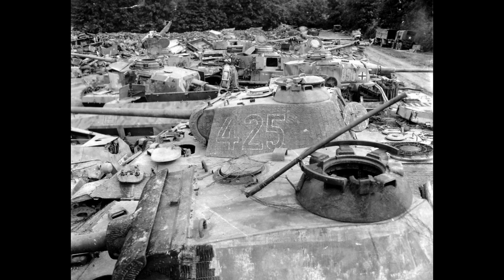Gears that looked acceptable on visual inspection but lacked the internal structure to resist fatigue failure. Some gears lasted longer than others, simply due to random variation in local material quality. But all were fundamentally inadequate for the application. Chen showed Harrington microscopic photographs of fracture surfaces from broken Panther gears.